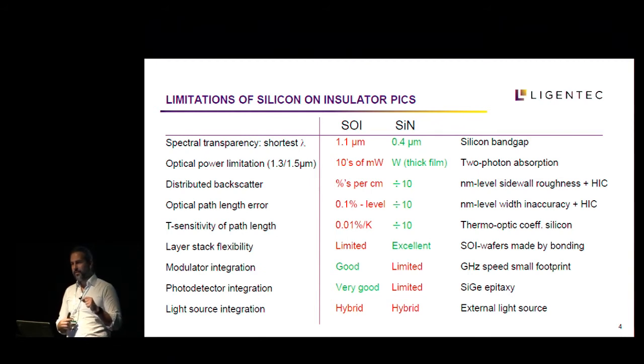But it also provides a unique opportunity for innovation, and that is to actually stack many layers of active functionality of waveguides, one on top of another, and make a full 3D circuit. In silicon nitride, the material is amorphous, so you can literally and readily deposit one layer on top of the other and have different functionality on each layer. In the SOI platform, that is not possible because of the crystalline silicon, you need to bond it, you need to transfer it from another crystalline wafer source.